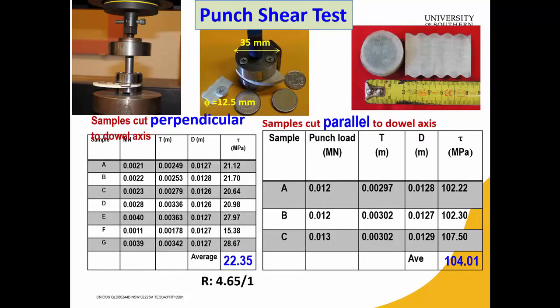Punch shear test was carried out to determine the axial and perpendicular shear strength of fiberglass dowels. Samples were cut parallel and perpendicular to the cross section of the sample. The small thin sample was positioned inside this punch shear testing, and the whole assembly was positioned inside the compression machine, and shear strength was determined.